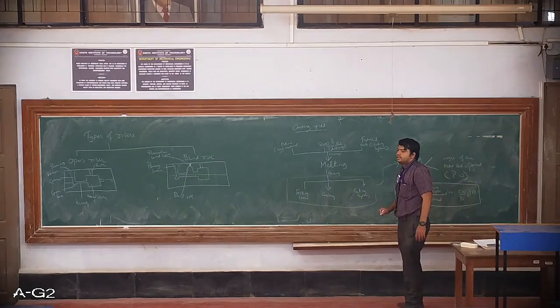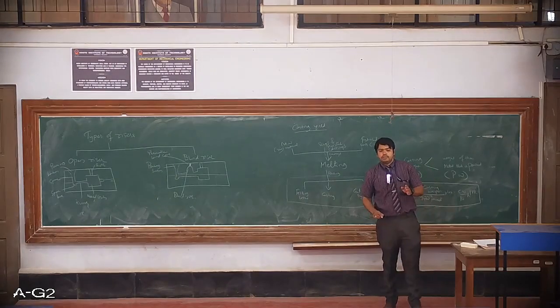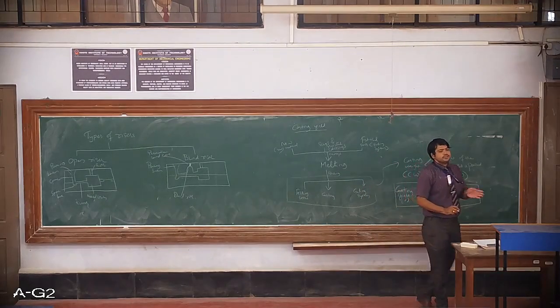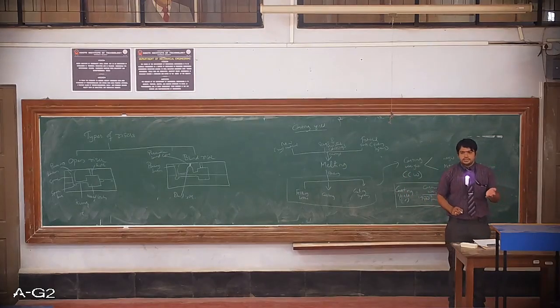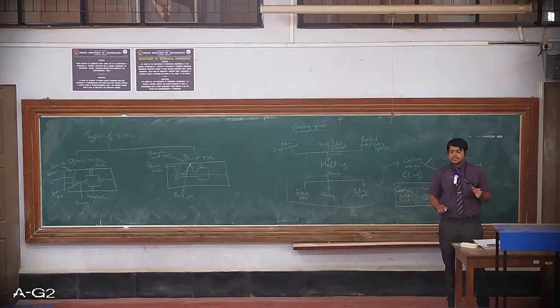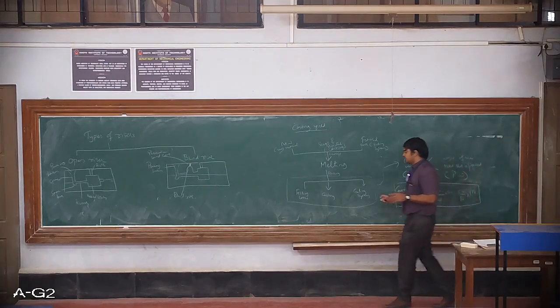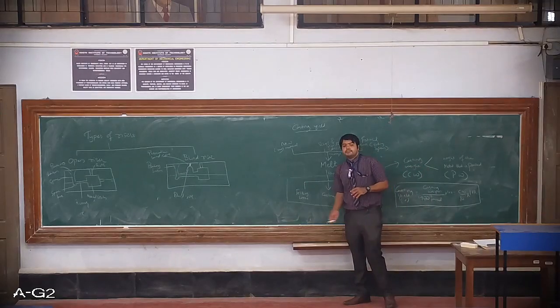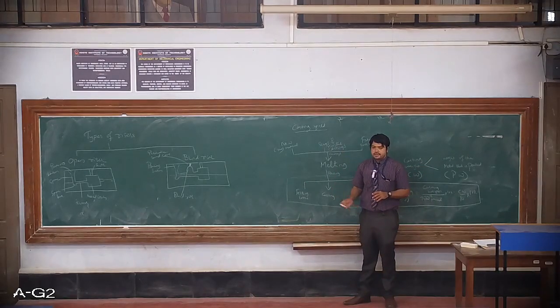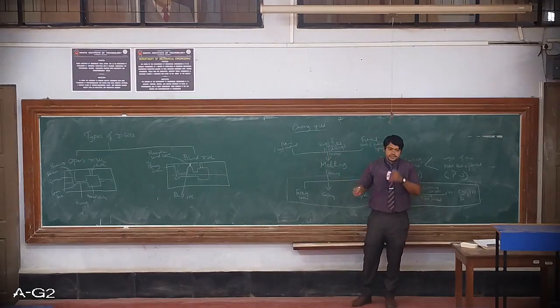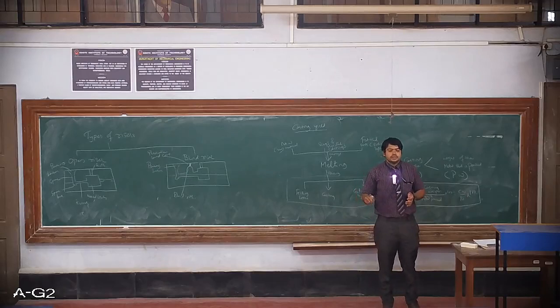Always remember, cast irons have good yield. It ranges from 70 to 75%, whereas for steel and other metals it is slightly less. As the riser requirement will be very less for cast iron, we have a very good casting yield. And here again, in fettling losses, I forgot to tell, the runner part and riser part are also used as input material or charge over here.